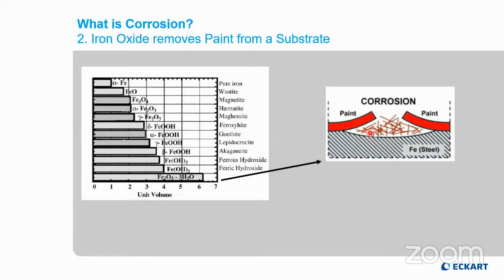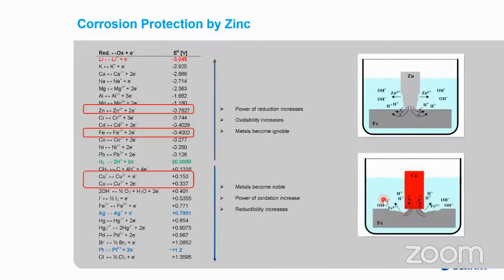The steel in that corrosion process is oxidized, disappears away, the paint is removed, and this rusting process is a big harm to the whole industry. How can this process be avoided? Well, by introduction of a metal, zinc, that is electrochemically more negative than iron. This particular metal is then oxidized instead of the iron, and the steel substrate is kept in place.